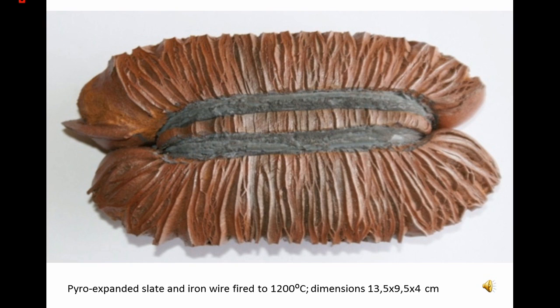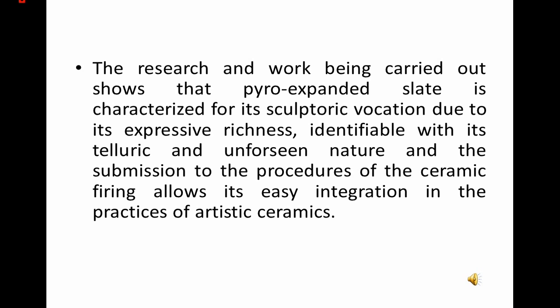Pyro-expanded slate structure gets close to the structure of some pyroclastic volcanic rocks, characterized by the existence of gas pockets, a fact that confers on them the capacity of floating in water, as happens with pumice. The existence of iron is fundamental for the transformation process since it conditions the fusion temperature, liberates oxygen at 1000 C, the temperature at which the glass is already formed, and also causes the color and the metallic aspect of surfaces. The technical process involved, the refractoriness being acquired, and its chemical composition indicate that pyro-expanded slate is a ceramic material.